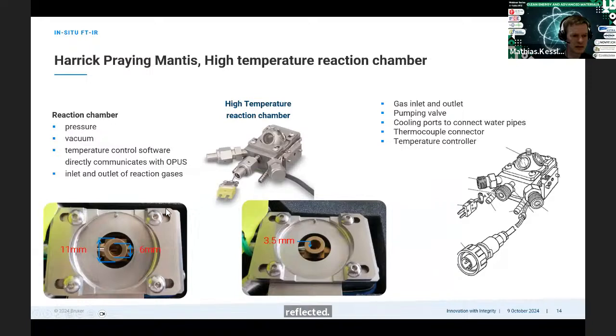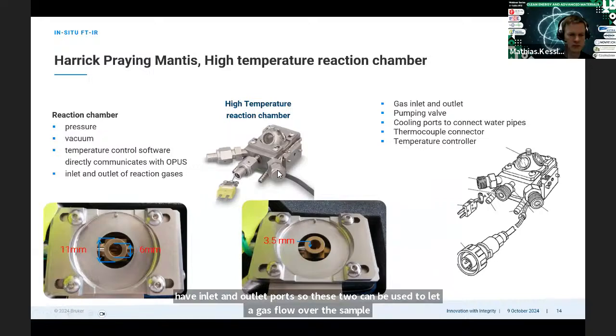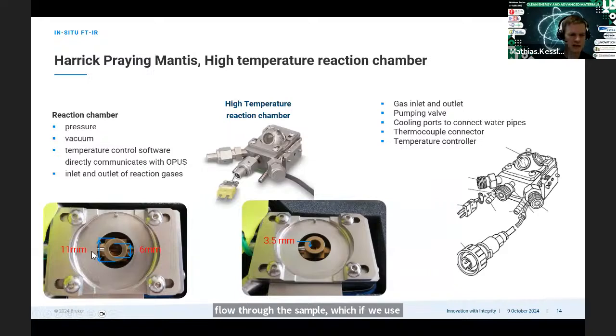If we have a look into the inner part of the cell, there we have our sample position. We place there a metal mesh, and on top of that we place then our sample powder. And of course, the reaction chamber can be used to change the pressure, to operate under vacuum, to change the temperature via control out of a special software, which also controls OPUS. We have inlet and outlet ports. So these 2 can be used to let the gas flow over the sample. We can also let the gas flow through the sample, if we use both of these connectors, then the gas is flowing through the powder. And we can also use just the middle port here to evacuate the reaction chamber. And in addition, we have a connector for our temperature controller and two connectors to cool the housing of the reaction cell with cooling water.